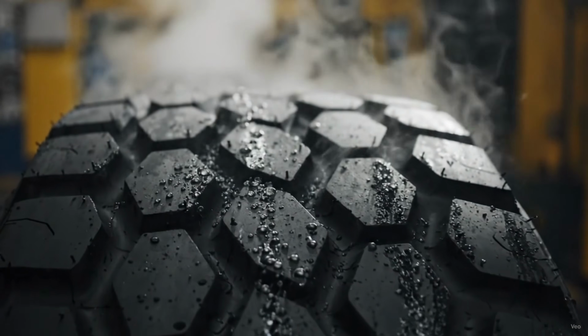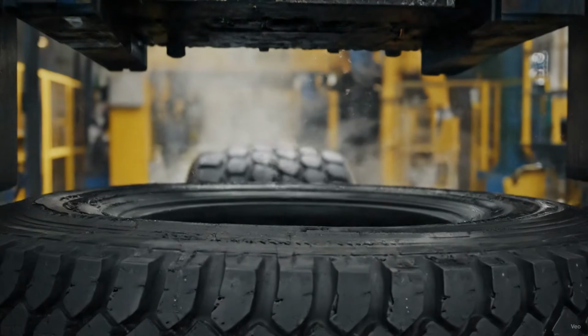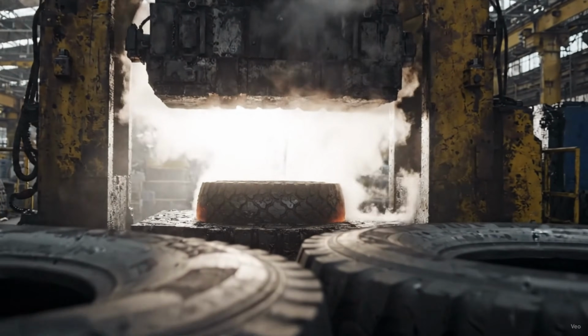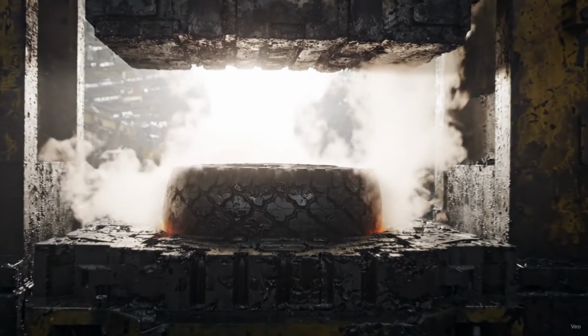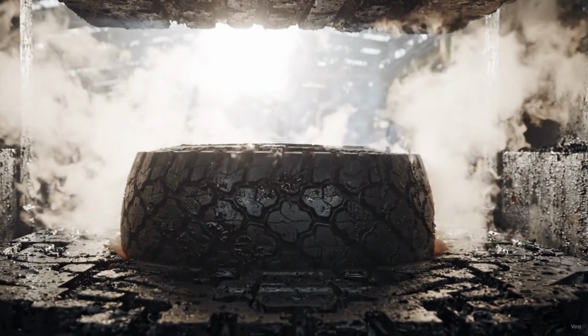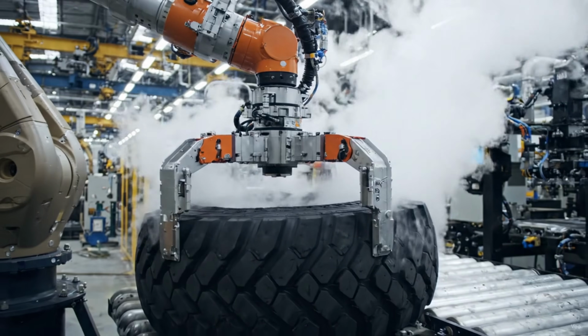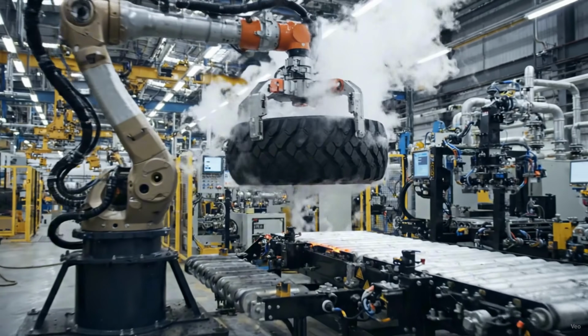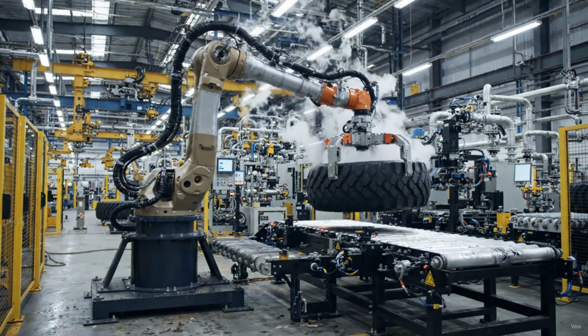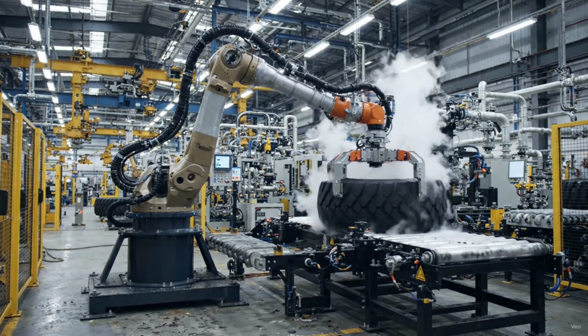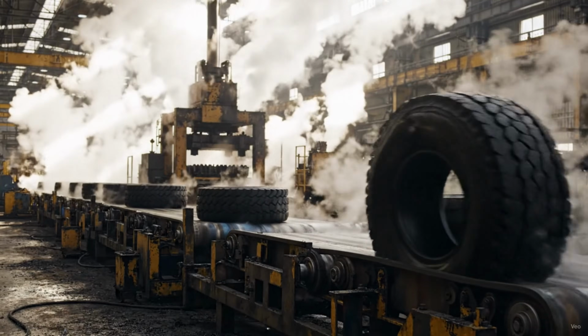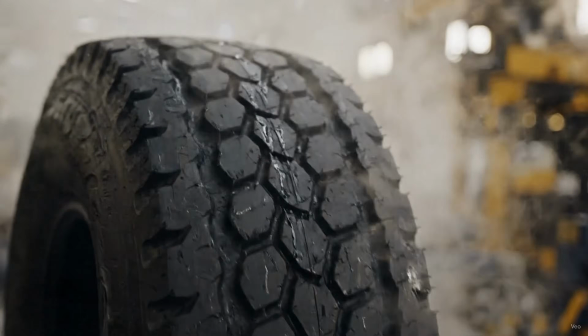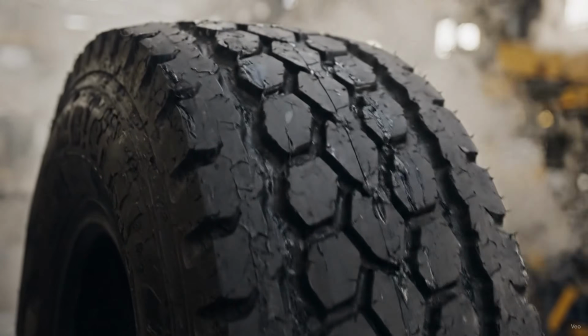This immense pressure forces the raw rubber deep into every intricate recess of the mold, under continuous heat ranging from 160 to 180 degrees Celsius, that creates strong crosslinks between the polymer chains. When the metal mold finally opens, the soft, sticky rubber has been transformed into a highly durable, heat-resistant elastic structure, now carrying sharply defined tread grooves and fully formed raised markings.